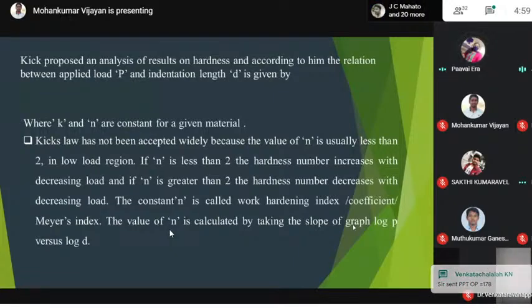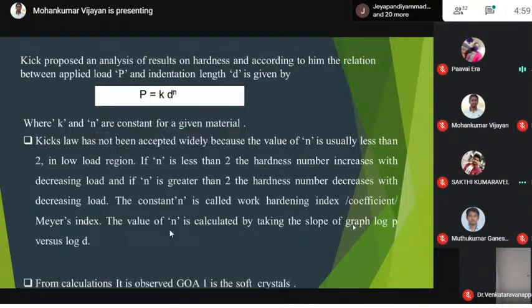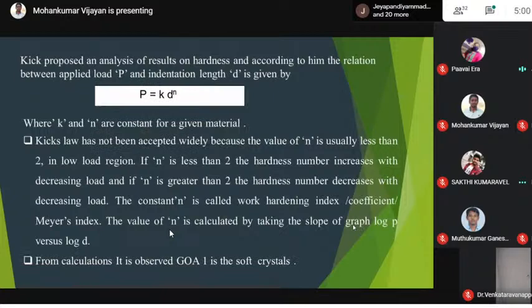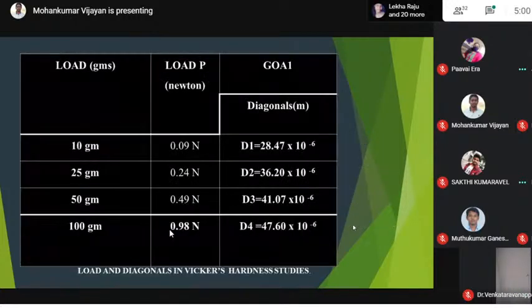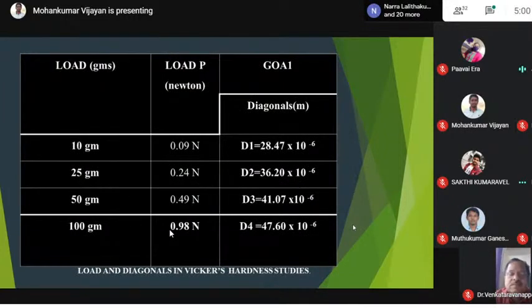And indentation length D is given by the formula. The formula is P is equal to K D raised to n, and from the calculation it is confirmed that the grown crystal GOA1 is a soft crystal. This is the observation table. For different loads, 10 gram, 25 gram, 50 gram and 100 gram, the GOA1 diagonal size is increasing.